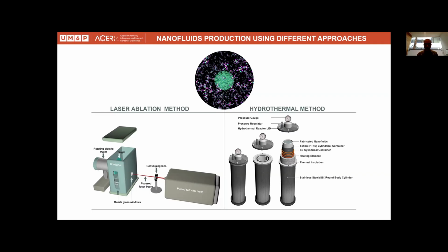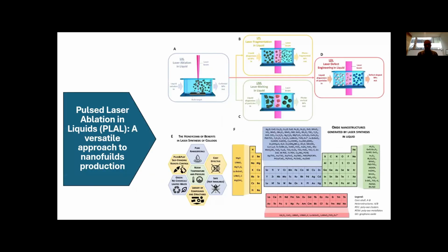When dealing with hydrothermal methods, sometimes it's difficult to control the size. We have a high size distribution, with bigger particles and smaller particles. It creates a lot of issues in terms of agglomeration and so on. So of course, we chose pulsed laser ablation in liquid because it has different advantages. You can use it to ablate metallic targets. You can use it for fragmentation, if you have bigger particles and want to make them smaller. You can do that with laser ablation.